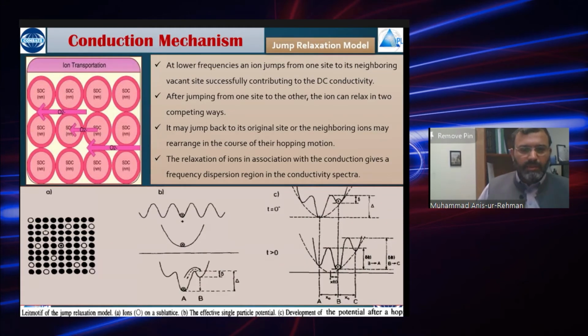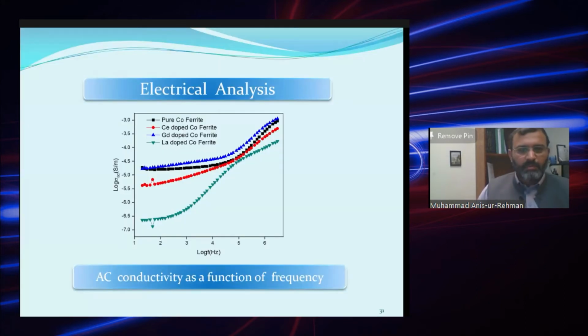What actually is happening is that when an ion gets a vacant site, it jumps to the next site, and if that site holds an ion, there is a change in the potential, as shown in the lower figure. As a result the ion moves on and on, and if it comes back, it means the jump was unsuccessful. So as we are increasing the frequency, more successful jumps are available as compared to the lower frequency mode. This is known as the jump relaxation model.